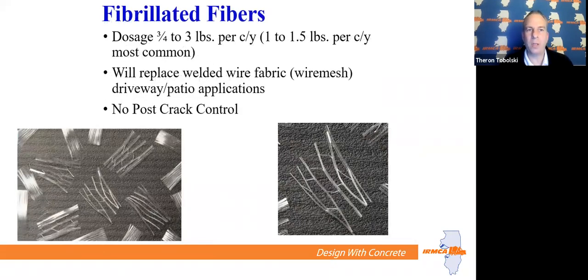The next type of fiber is what we call fibrillated fiber. 3/4 to 3 pounds per cubic yard is the standard range for this fiber. 1 to 1.5 is typically what we see people use. It will replace welded wire fabric in driveways or patios, but it has no post-crack control. And what that means is, everybody in this industry defaults to welded wire mesh. It really doesn't do much for you. Welded wire mesh does not stop cracks from happening. The only thing welded wire fabric does is, once a crack happens, it holds it together.